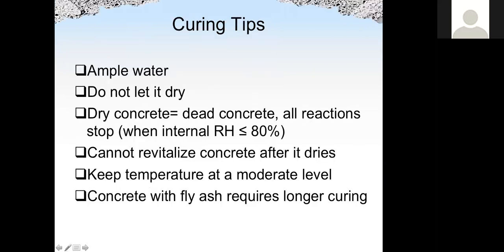So for curing, the tips are we need to provide a lot of water for long enough time. The longer, the better. Do not let the concrete dry, at least for the first 5 to 7 days. Remember, dry concrete is equal to dead concrete, which means no hydration will go on. All the chemical reactions will stop when the internal relative humidity is less than 80%. If the concrete dries out, we cannot revitalize it, even if we put the concrete back into water. So remember that.